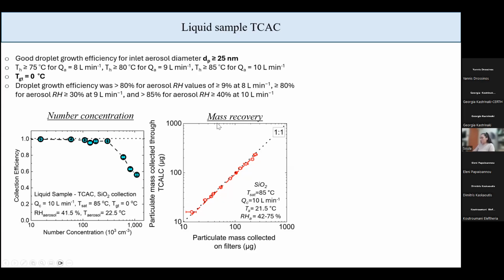And the next plot shows the mass recovery. It was obtained by doing the following experiment. I had one line where the liquid sampler was collecting sample at 10 liters per minute. And in parallel, I had a 37 mm particulate filter collecting the same sample at 10 liters per minute. So on the x-axis is the mass that was collected on the filter, and on the y-axis is the mass that was collected on the liquid sampler.